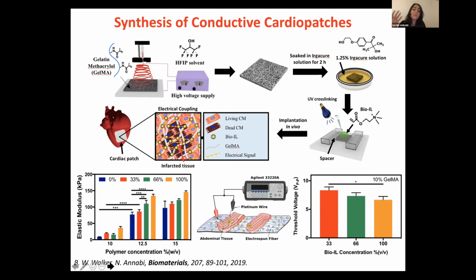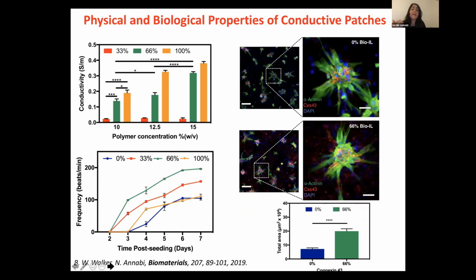To further explore this, in vitro, we extracted cardiomyocytes from rat hearts, and these cells were cultured on the biomaterial with different levels of conductivity. One advantage with this technology is that we can finely tune the level of the conductivity in biomaterial by simply changing the bioionic liquid concentration.